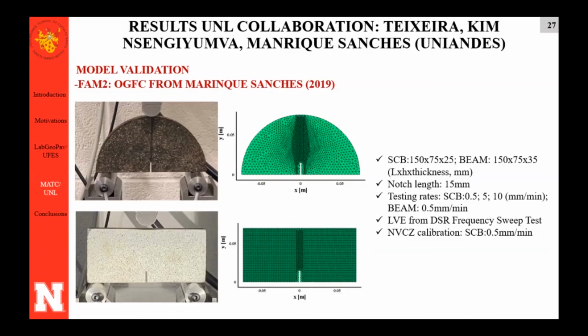She also obtained her linear viscoelastic properties from DSR frequency sweep test. And we took this data, and Gabrielle Nisan-Guilluman helped us here with the laboratory test. So it's also a collaborator on this part of the test. And we calibrate her test from the SCB that we use for calibration. That's our approach to use this model.